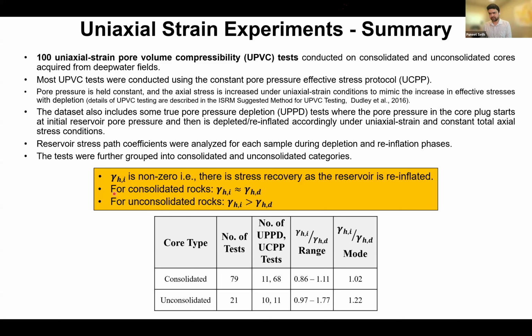What is very interesting is that for stiff or consolidated rocks, the injection coefficient is very similar to the depletion coefficient, sometimes almost exactly the same. For unconsolidated or soft rocks, the injection coefficient is actually higher than the depletion coefficient. So this is a summary of the tests. As I said, 79 were consolidated, 21 unconsolidated. This is a distribution of which ones were with one protocol versus the other, the true pore pressure versus the constant pore pressure effective stress.